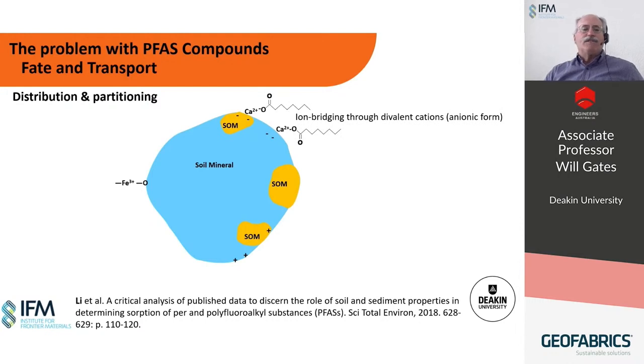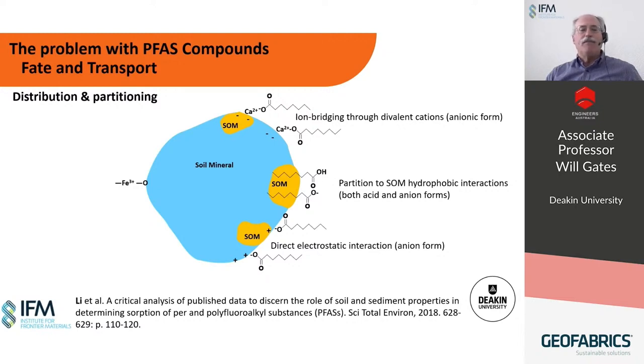The various forms of interplay result in ion bridging. So if there's a positively charged organic carbon, you can expect to see some ionic bridging, just as we saw for the positive mineral form. We also have direct electrostatic interactions. That would be important in the case where the pH is above the pKa of the PFAS compound. In situations where the pH is not above the pKa of the molecule, then we can expect that other adsorptions such as phase partitioning interactions can take place. Covalent bonding, such as directly to surfaces, appears to be fairly rarely observed for PFAS compounds.